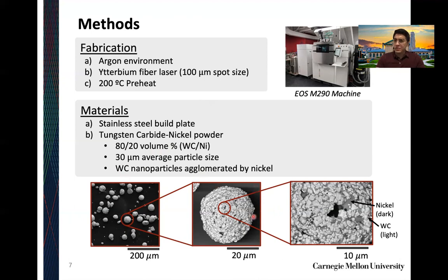But if you actually look very closely at this powder, the powder itself is almost like a pseudo particle composed of tungsten carbide nanoparticles below 1 micron in diameter. And these nanoparticles are embedded within an agglomerated ball of nickel. So if you look at these SEMs down here, you see how spherical these powder particles really are. And as we zoom in, the nickel phase, which is in dark, is really just an agglomerated ball, and then within it you have embedded tungsten carbide or light gray particles in there, which is very unique because this is a new material or new powder system that we actually haven't seen before. So we were very excited to try this out.